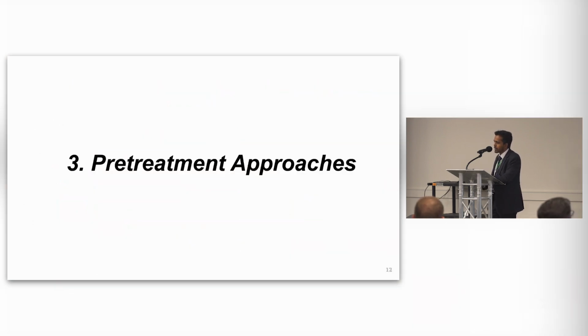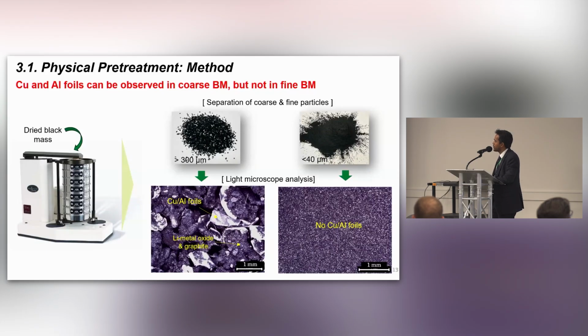Now let's move into some highlights related to the pre-treatment approaches. We have attempted to separate some impurities using basic physical pre-treatment technologies such as screening. We used the dried black mass. Here you can see we separated the coarse particles over 300 micrometers, which basically contain a lot of copper and aluminum foils, and the fine particles less than 40 micrometers. In this section, we couldn't observe any copper and aluminum foils, and this is actually the majority of the black mass, representing 90% of the black mass weight.